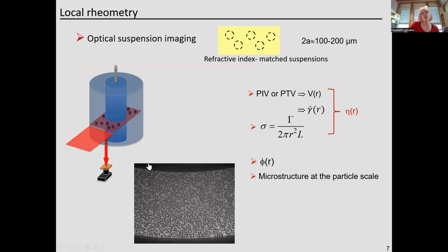And you can also use suspension imaging, and it is what we have developed in Nice because it's a much easier and cheaper technique. But of course, the drawback of this technique is that you have to use transparent suspension. So you have to match the refractive index of the particles and the refractive index of the suspending liquid. So you cannot study real suspensions. You have to make your own suspensions to make local rheometry with optical suspension imaging. But with this transparent suspension, it's really easy to make local rheometry measurements.